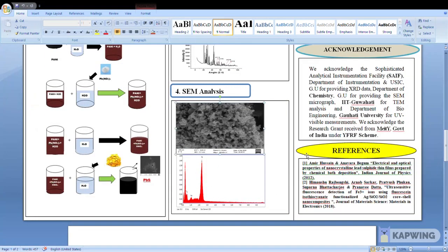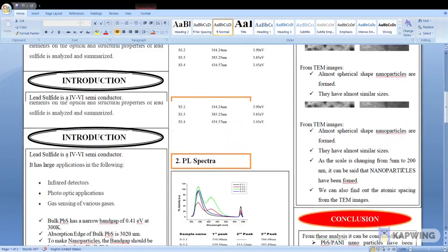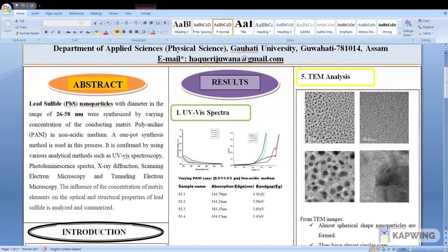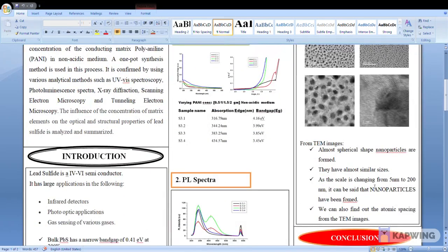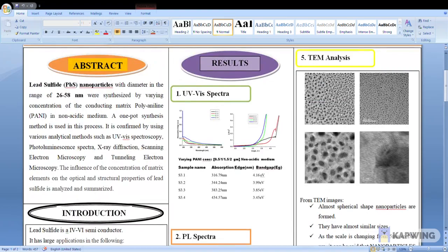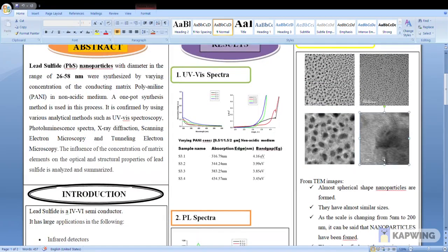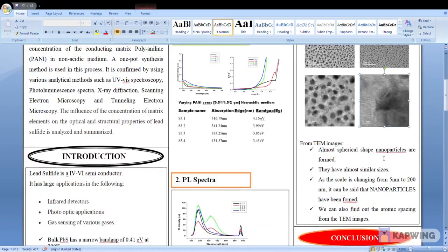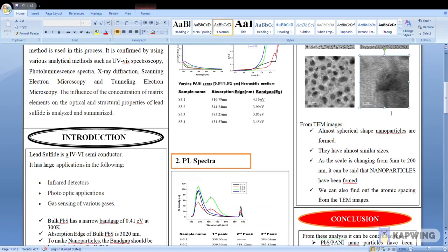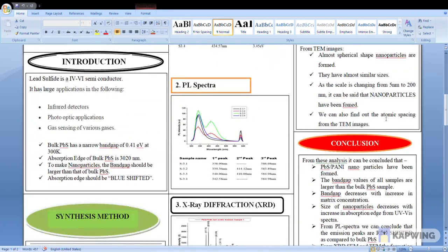From the TEM images, you can see that almost spherical shape of nanoparticles are formed, as they have almost similar sizes. As the scale is changing from 5 nanometer to 200 nanometer, it can be visibly seen that nanoparticles have been formed. We can also find the interatomic spacing with the help of TEM images.